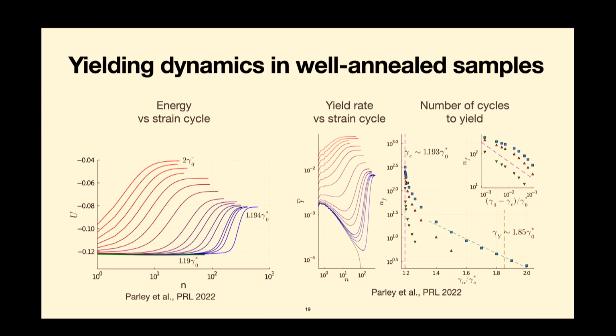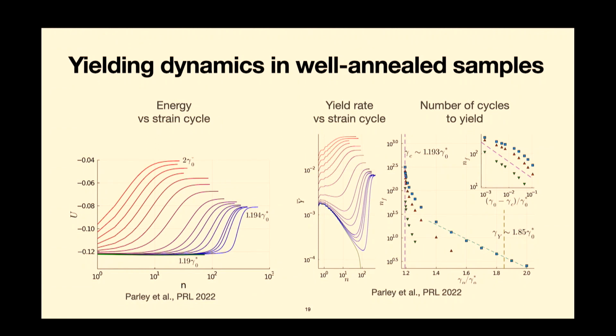So the energy already shows you that something interesting is happening. More interesting is if you look at this from the point of view of the yield rate. So you ask how many events are happening in each strain cycle, essentially. That's the period average quantity from before, so that's why it has these slight wiggles here at the beginning. You see that up at high strain amplitudes, much what you'd expect happens. The yield rate goes up from the beginning and reaches a fluidized state. But what's interesting is this regime in between here, where the yield rate first goes down, and then eventually you very rapidly reach this fluidized state.